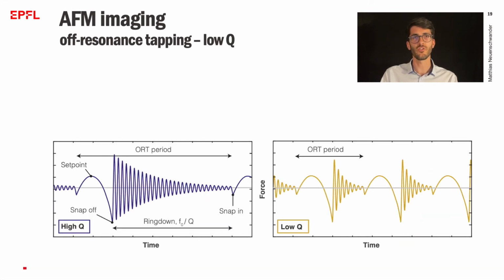When imaging at such high rates, some new problems can turn up. One of them is cantilever ringing. When the cantilever snaps off the surface, it rings at its resonant frequency. The amplitude decays exponentially, and the ring down time depends on the quality factor of the cantilever. If the lever is still ringing when snapping onto the surface for the next cycle, all the energy is dissipated into the sample and can damage both the sample and the tip. To avoid this, we need to keep the off-resonance tapping period long enough to ensure a complete ring down.